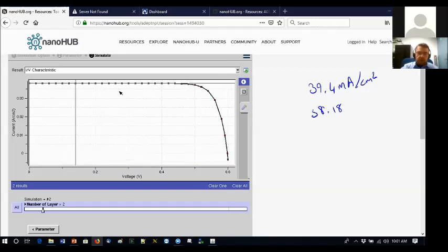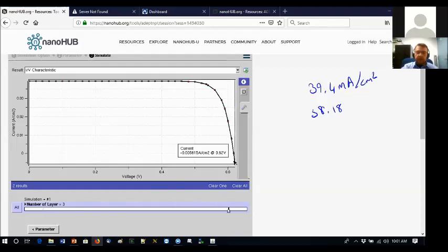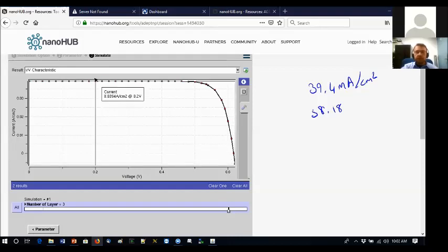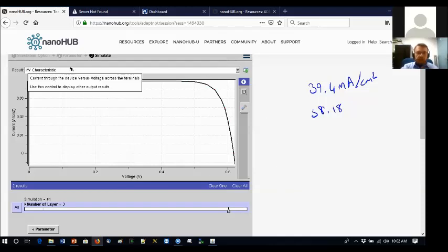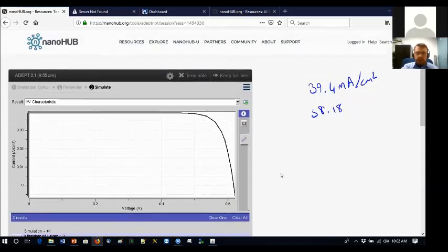So these are the open circuit voltage and the short circuit current, the crossing points of the X and Y axis, basically. These are the two important parameters because my solar cell efficiency is related to the multiplication of these two. It's 0.6 here. The higher, the better. When I put the barrier, the new layer, it jumps up to 0.62, and the current also jumps up too. See? This immediately shows us how we can increase the performance of the solar cell.